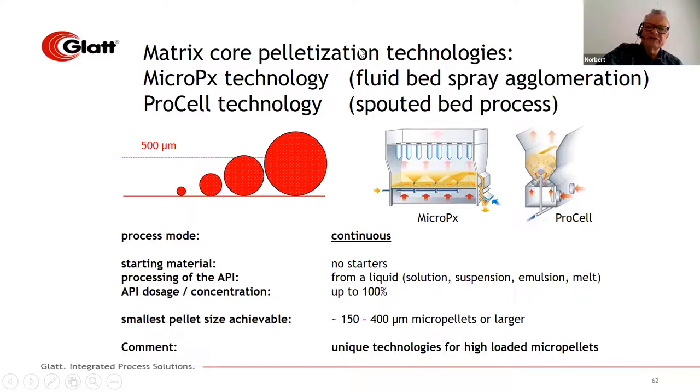The one is a fluid bed spray agglomeration process, the Micropx. We have a rectangular shaped processing chamber. We have bottom spray nozzles, and we have in this case a zigzag discharge unit, which is controlling the particle size by sifting air. And on the right side, we have the so-called ProCell technology. You see, it looks completely different from the installation, from the air distribution into the processing chamber. It's a so-called spouted bed technology. Both are continuous processes. Both are providing matrix pellets, so we need no starters. And both are processing the API, most of the time including a binder,